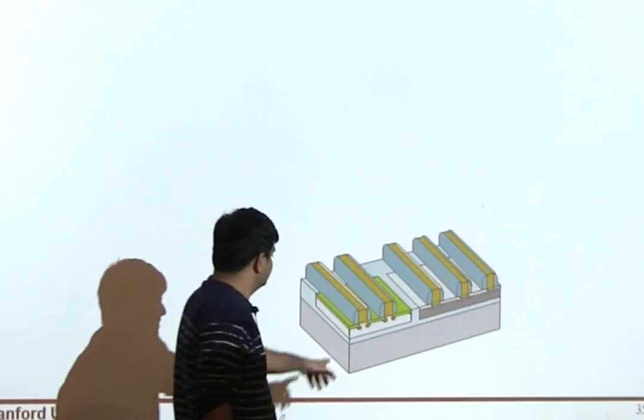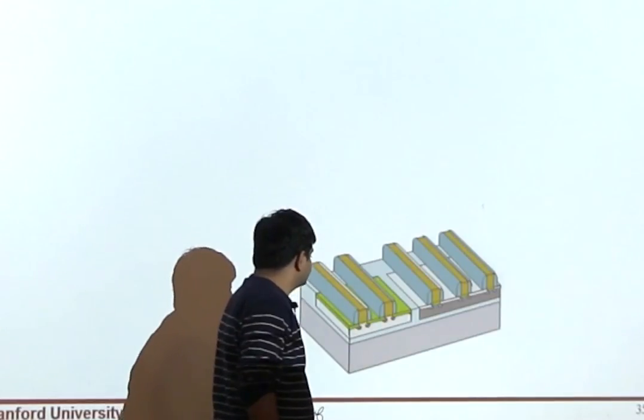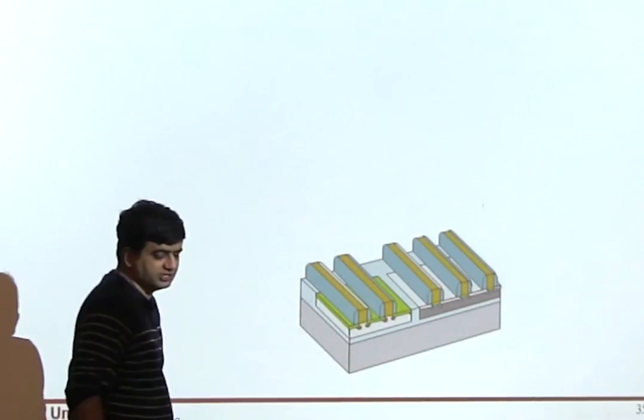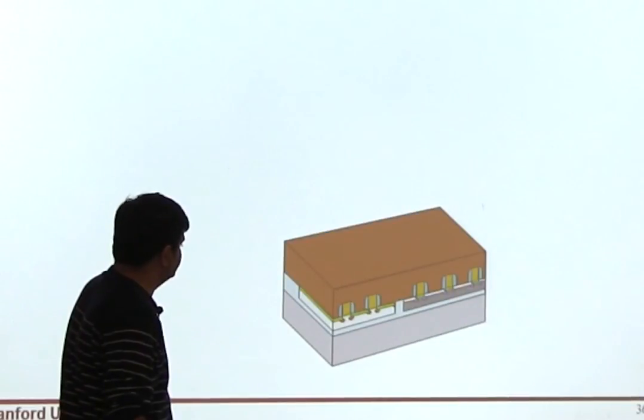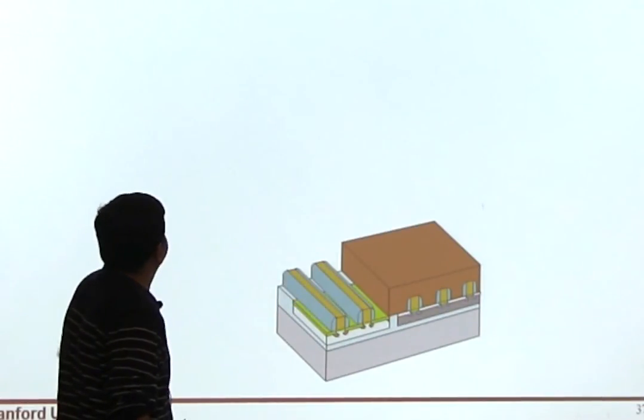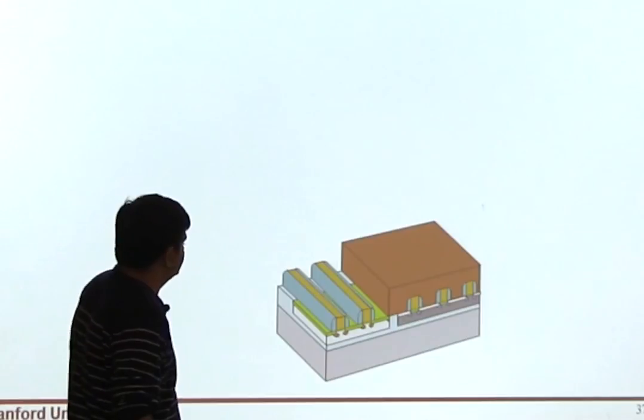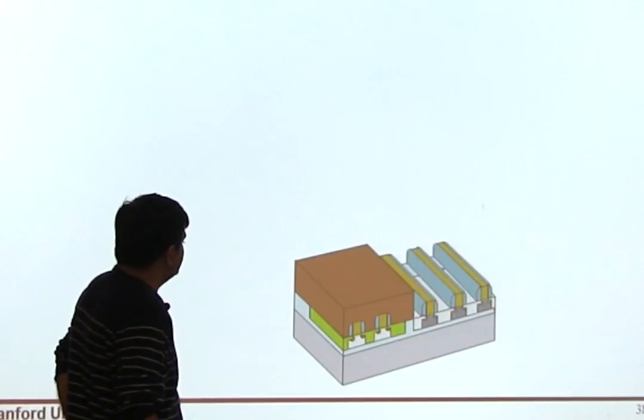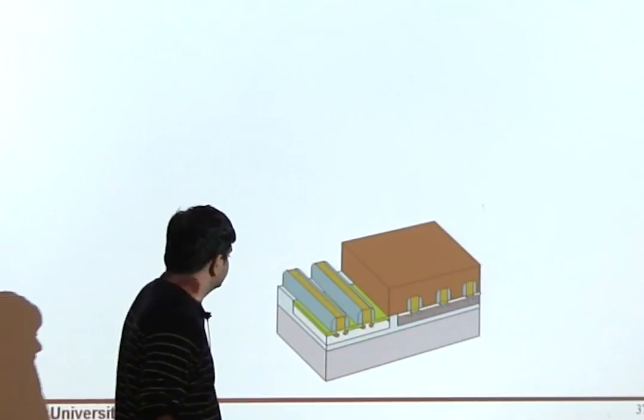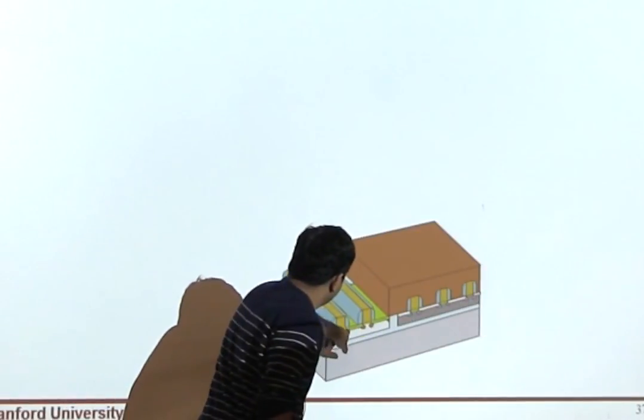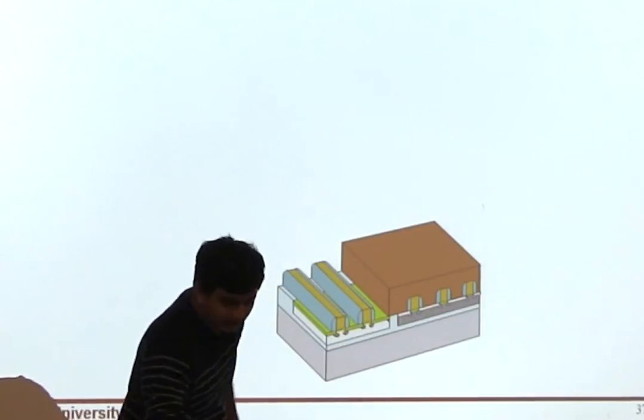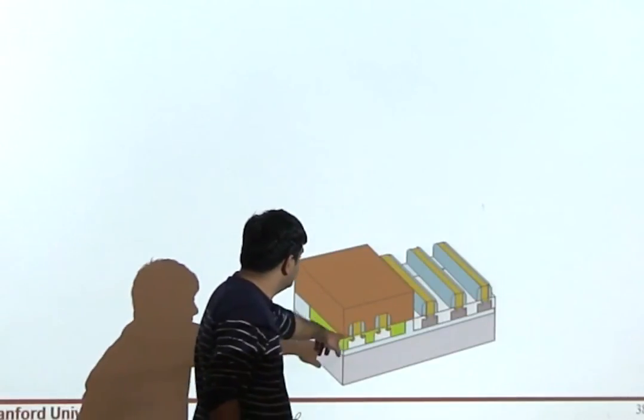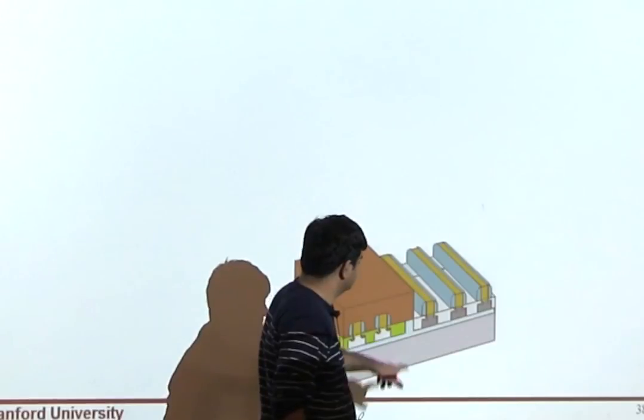So you're left with this spacer, and this spacer helps us to do the next set of implants. So now we again cover it with photoresist, open up the region where you have PFETs, and then do these higher energy implants. This shows the shallow implant region and then the deeper region from the higher energy implants.